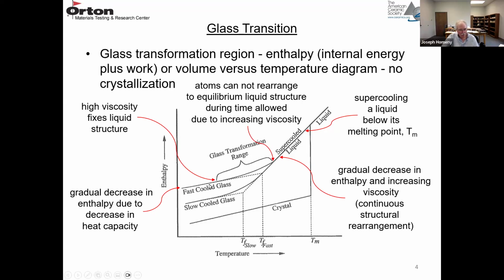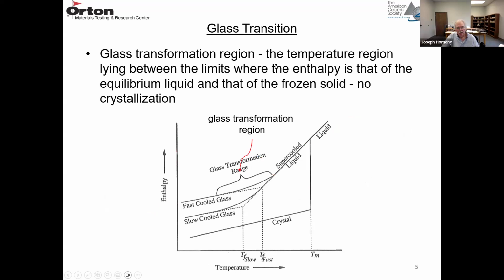And then after that temperature is reached, you just have a gradual decrease in the enthalpy as the heat capacity decreases with decreasing temperature. So here's your glass transformation range. So this is the temperature region lying between these limits where the enthalpy is that of the equilibrium liquid and that of the frozen solid. So those are the two endpoints for the glass transformation region.